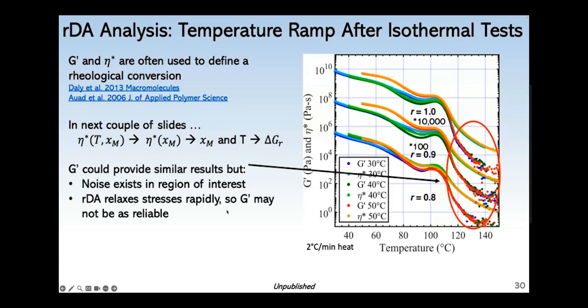And G prime might have provided similar results, but one problem is that where I would want to perform the equilibrium analysis, there's a lot of noise in G prime since it's degelled and the network's no longer present. And then at these temperatures too, RDA reactions relax stresses quickly. So G prime might not be as reliable without some additional correction.